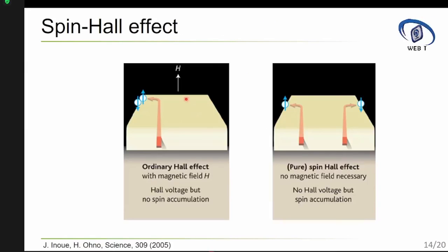There is a spin Hall effect, which is different from the ordinary Hall effect. In the ordinary Hall effect, you apply a perpendicular magnetic field, you create some deflection of electrons, and then you have some Hall voltage. However, in the spin Hall effect, you don't need an applied magnetic field. If it's a heavy metal, spin up electrons will deflect in one direction and spin down electrons will deflect in the other direction. This has a lot of consequences.